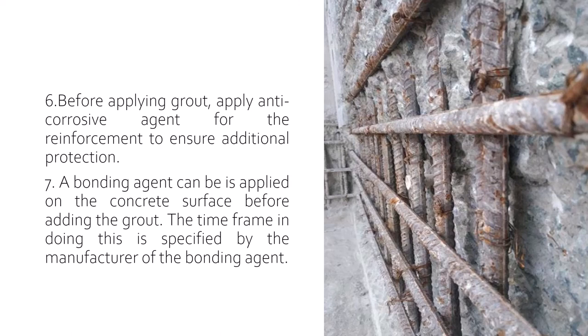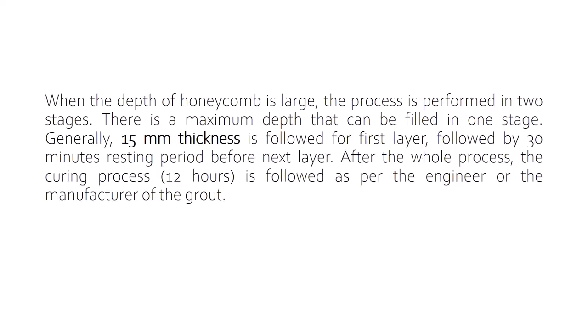When the depth of honeycomb is large, the process is performed in two stages. The maximum depth that can be filled in a single step is generally 15 mm thickness, followed by a second layer after 30 minutes. After the whole process is complete, a curing process is performed for around 12 hours, as per the engineer's or manufacturer's guidance. The curing process is performed either using a plastic wrap or any covering as per the traditional method of curing concrete structures.